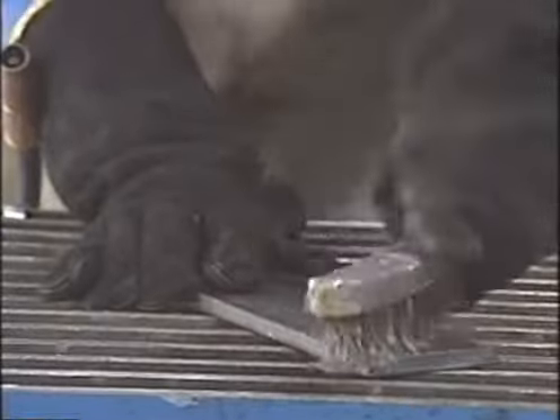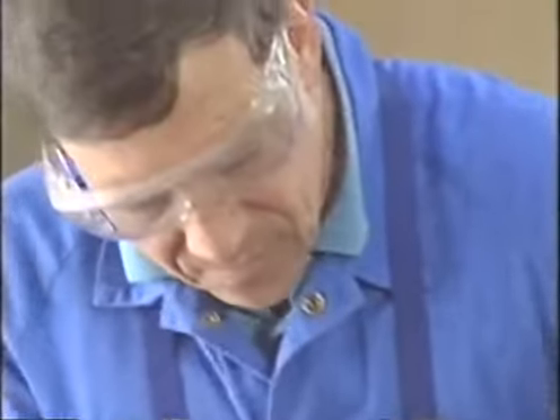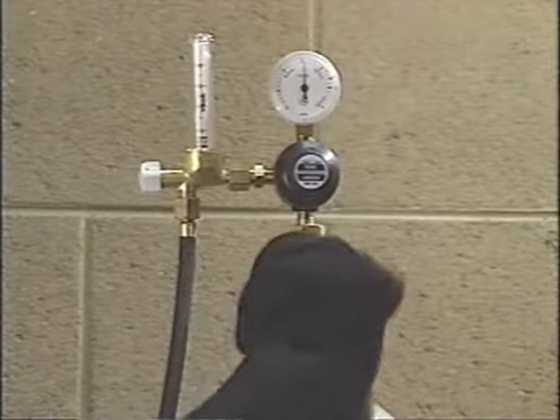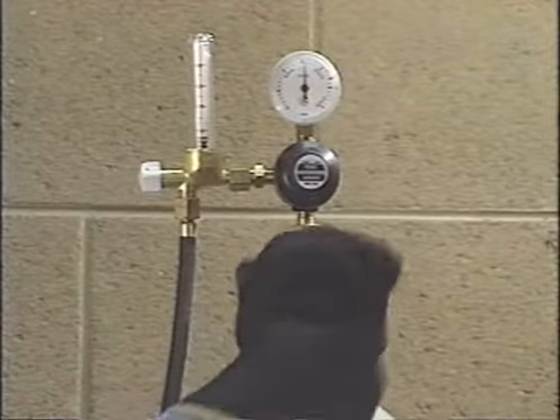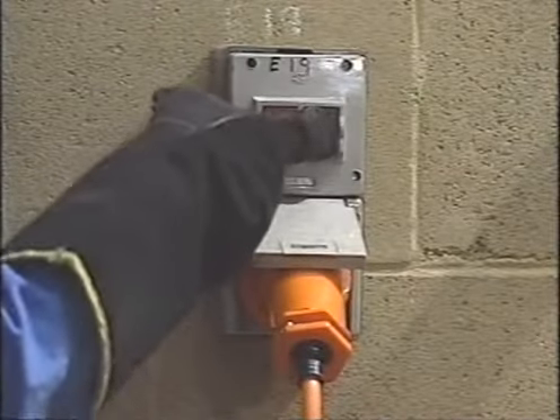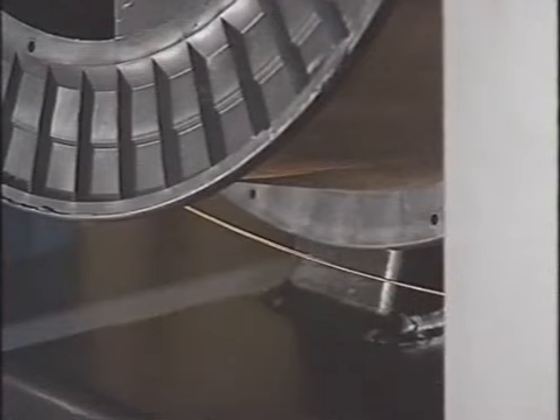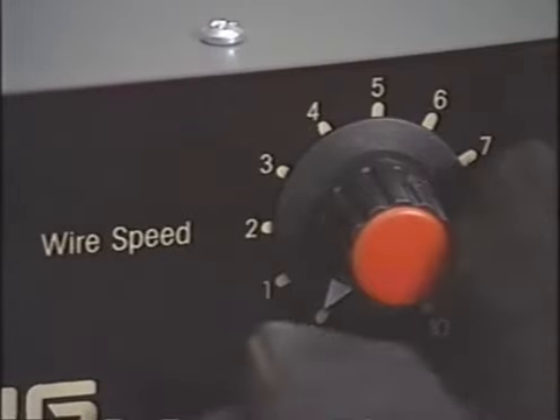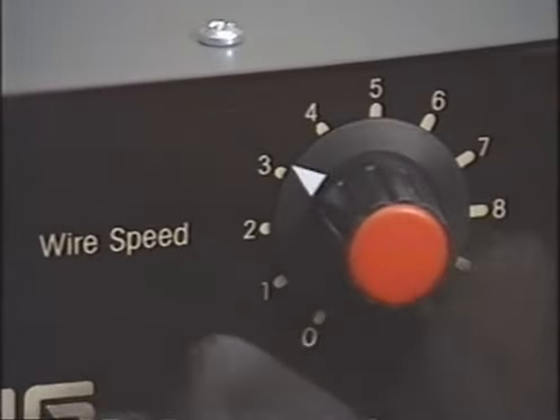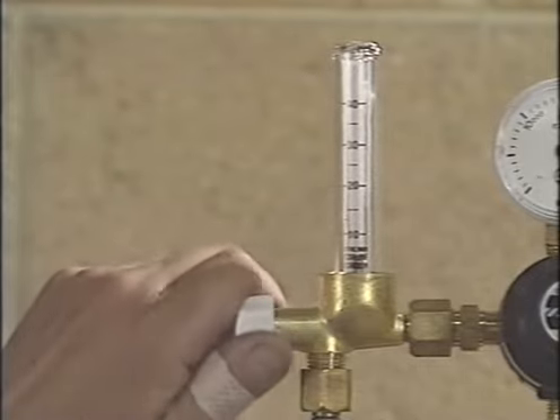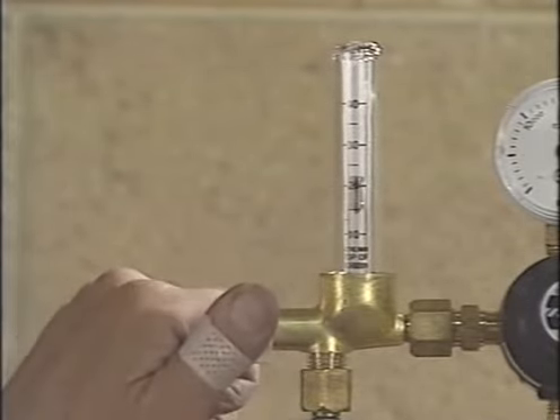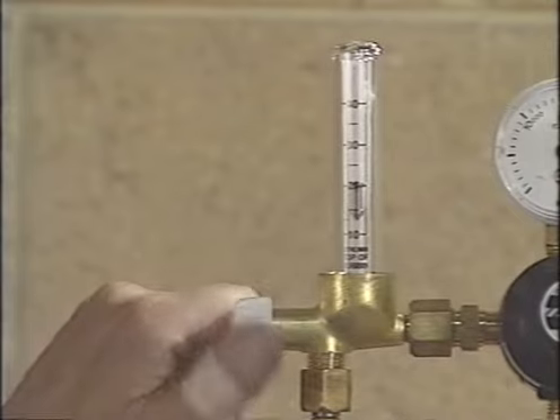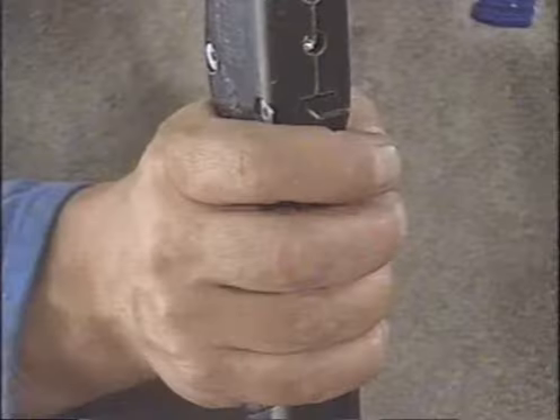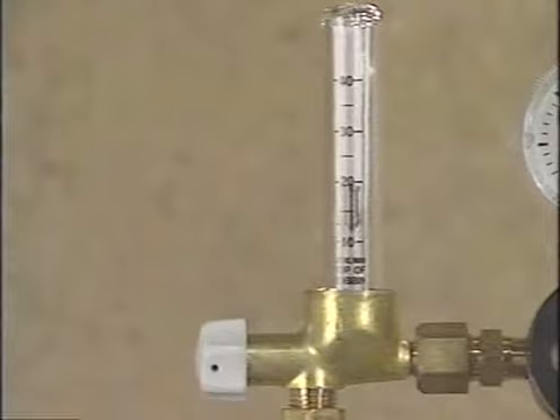Wire brush the metal to be welded to remove any rust, grease or paint. Open the gas cylinder. Switch the welding machine on. Set the voltage. We will use a wire thickness of 0.9 millimetres. Adjust the wire speed appropriately. Using the gas flow meter, adjust the flow rate to 12 litres per minute. To check the flow rate, depress the trigger on the welding gun.